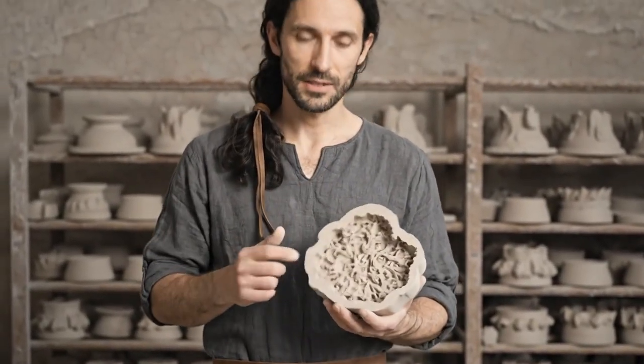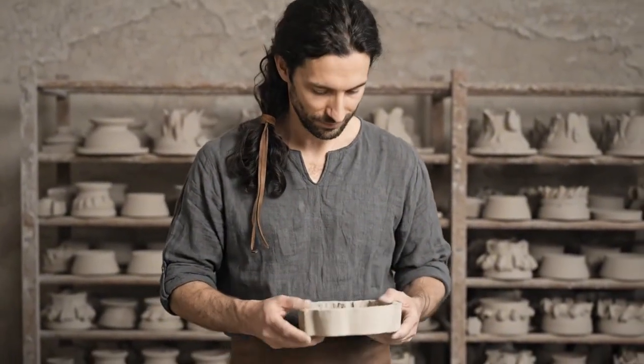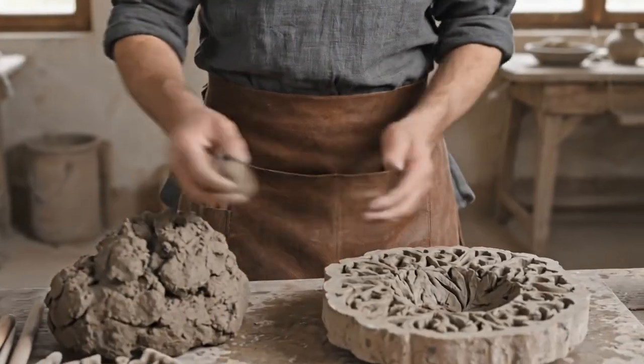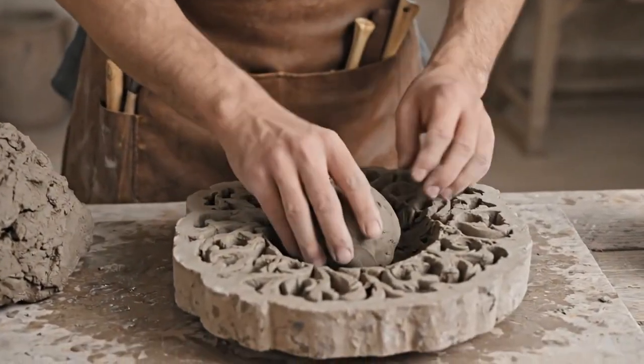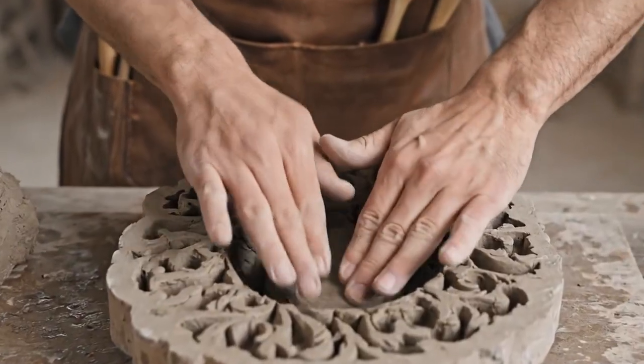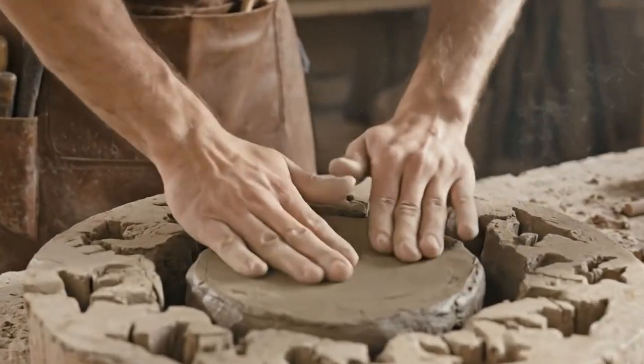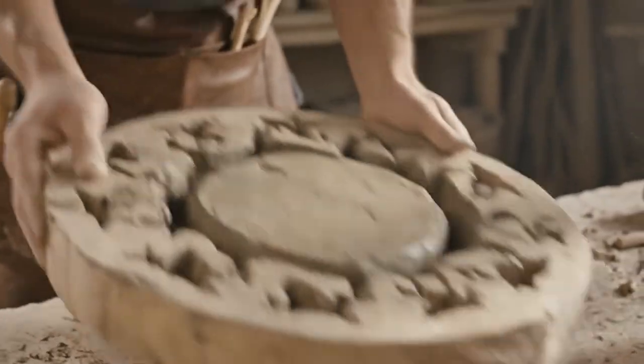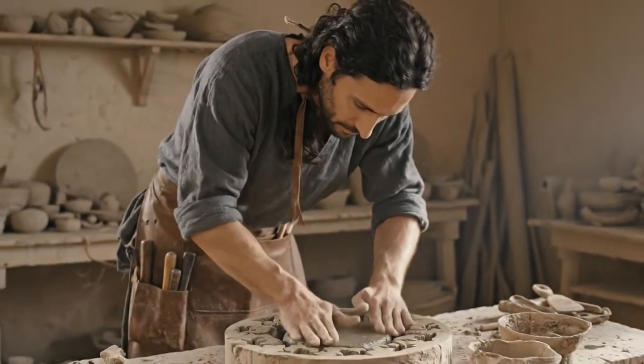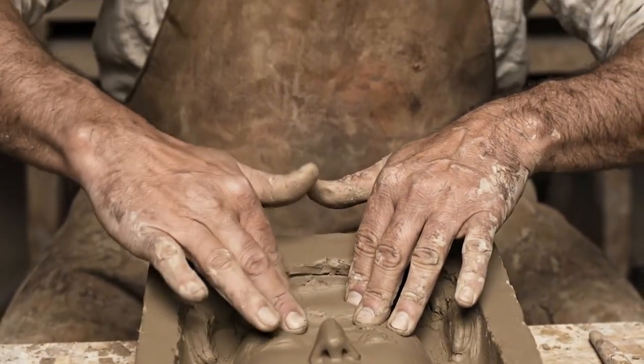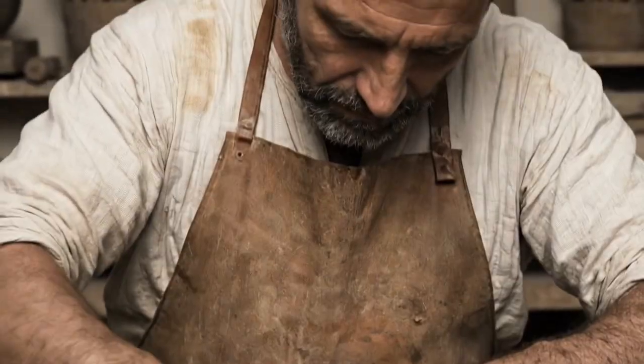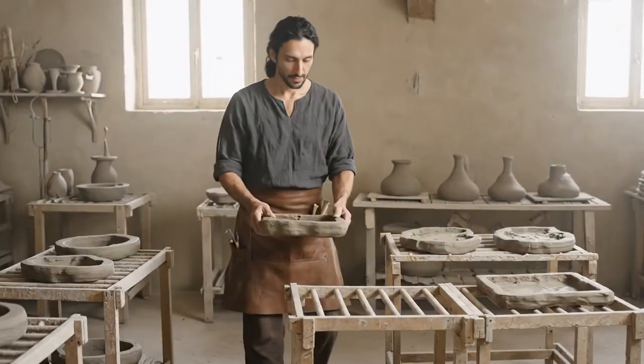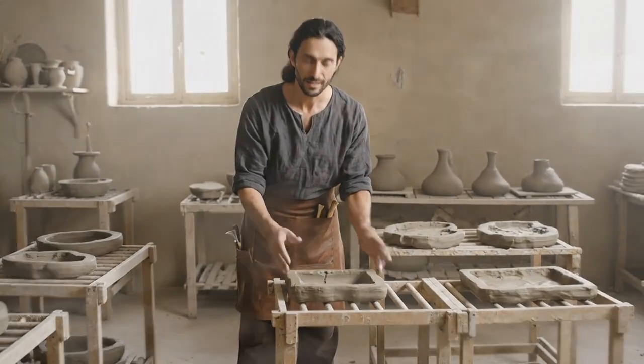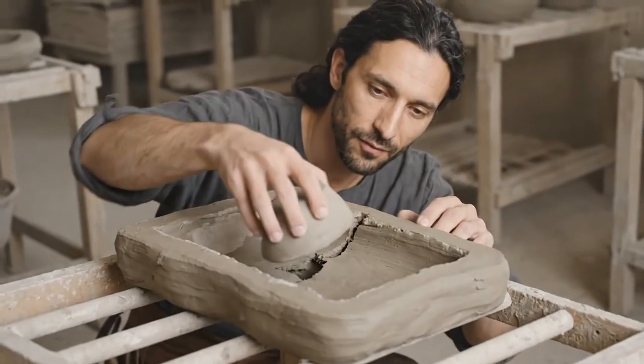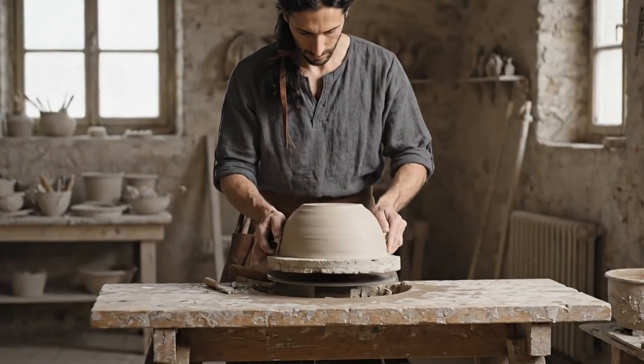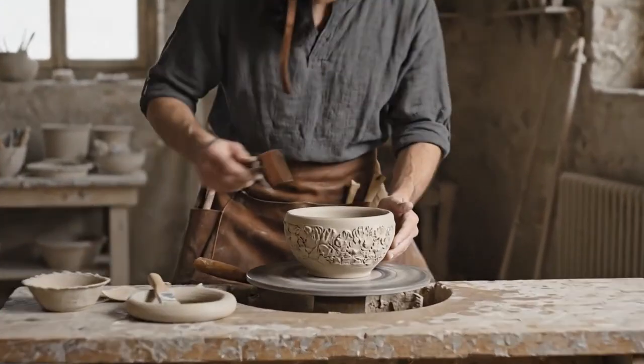A potter takes a measured ball of refined clay body, not the colloidal slip, but the denser fine middle fraction from the levigation, and pushes it firmly into the interior of the fired mold, working outward from the center with his thumbs, forcing the clay into every poinçon impression, every stylus groove. He must apply even pressure. Too much in one spot, and the wall thins dangerously. Too little and a figure's face blurs into anonymity. As the pressed clay dries, it shrinks, and this shrinkage is the ingenious mechanism that allows the bowl to release cleanly from the mold without distorting the decoration.